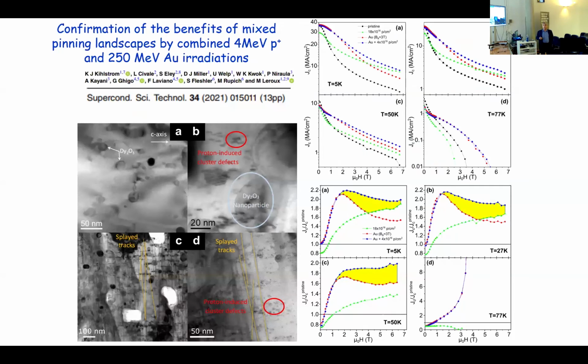Let me go quickly to this example where we wanted to show if it is also true that mixed pinning landscapes are a general rule to improve pinning. In this one, we combined this 4 MeV proton irradiation, not at the optimum dose, a little bit less, just not to saturate. And then we introduced columnar defects by heavy ion irradiation.